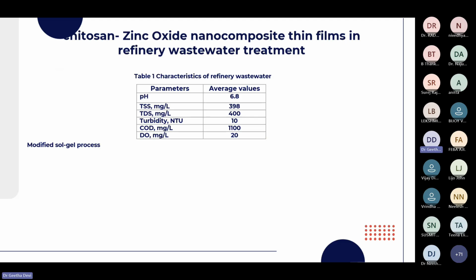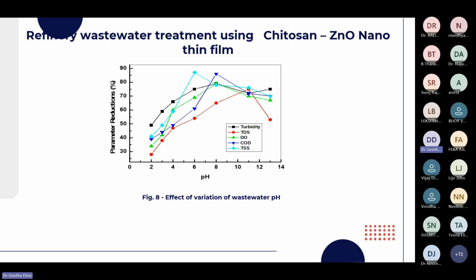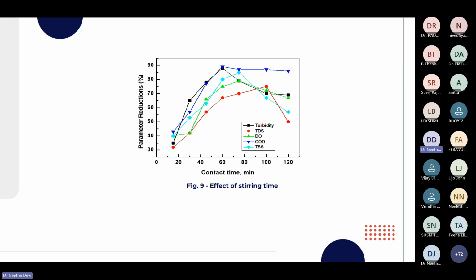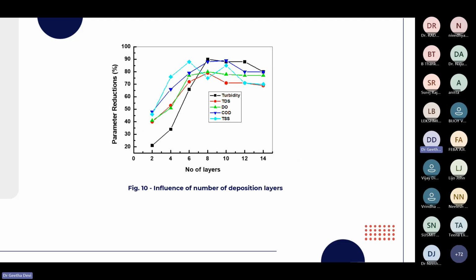And we have used this nano coating for refinery wastewater. The refinery wastewater was collected from the PDO outlet. And the effect of variation of pH is shown here, and the stirring time. Here also the number of deposition layers were varied, and we have investigated the percentage reduction in parameters.